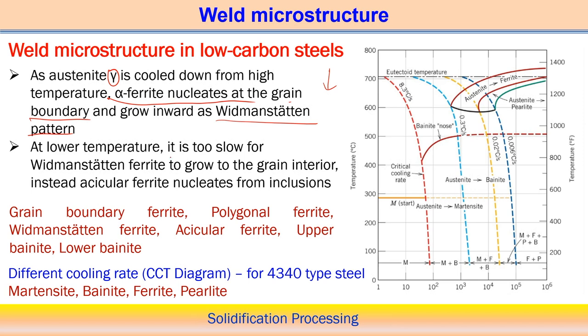But at the low temperature, it is too slow for the Widmanstatten ferrite to grow. In that case, within the grain interior, instead of this particular ferrite, acicular ferrite can nucleate, from inclusions. I mean to say that in one particular material the cooling rates are different, going from the high temperature zone gradually to the low temperature zone, and the morphology can be different. Even at low temperature, when the cooling rate is very slow, the morphology can also be different.